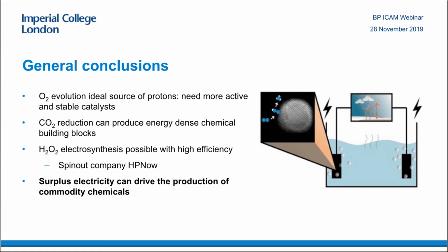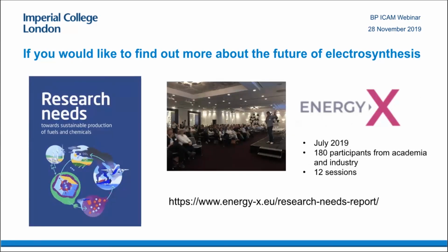CO2 reduction can produce energy-dense chemical building blocks. There's been huge progress made. There's still some more scope before it can really be industrialized, but it looks very promising. Hydrogen peroxide synthesis is possible using electrochemistry with high efficiency. We set up a spin-off company to commercialize it. The more important take-home message is that electrochemistry has the potential to make many of our most coveted chemicals.